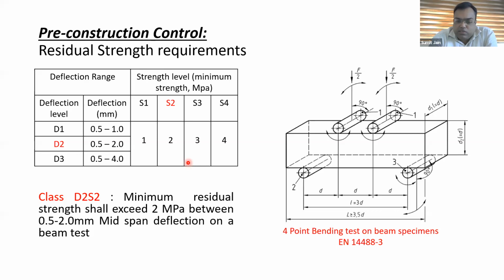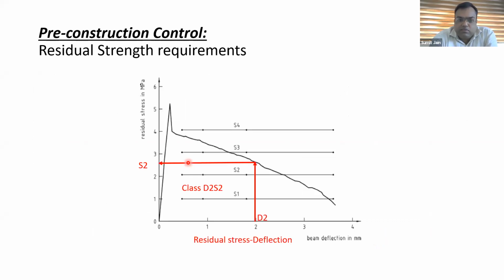And we'll just see how the graph plots when we are testing this specimen. So this is the graph plotting, and as you can see, the strength is gradually decreasing with the increase in deflection. In the area between 0.5 mm and 2 mm for a D2 categorization, this graph should lie above 2 MPa. This is the 2 MPa line, this is the strength class line, and these are the deflection class lines. So in this case, the graph plotted for residual stress versus deflection categorizes as a D2S2 class, because all parts of this curve lie above 2 MPa.